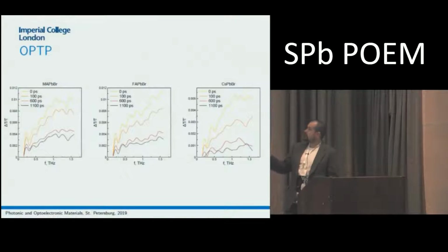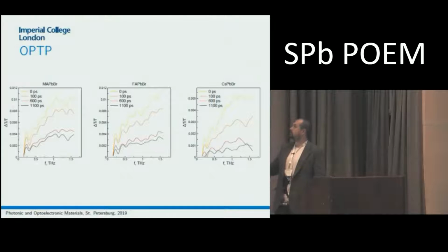So then we turned to a more thorough, more systematic study. We looked into bromides only, so we have methylammonium, formamidinium, and cesium lead bromides, and we looked into the spectra. This is the change of transmission normalized to the terahertz spectrum at different time delays: just after the pump, maybe it's not really visible, but it's a yellow curve, then 100 picoseconds, 600 picoseconds, and 1100 picoseconds after the pump.